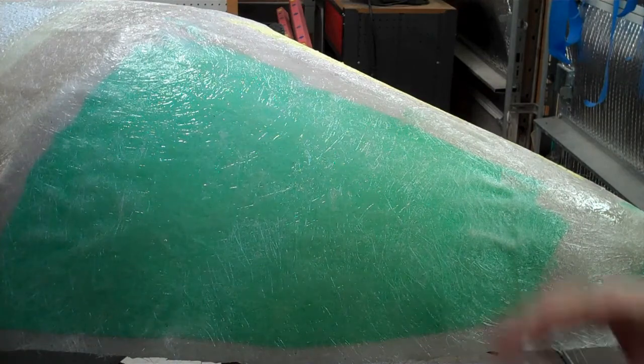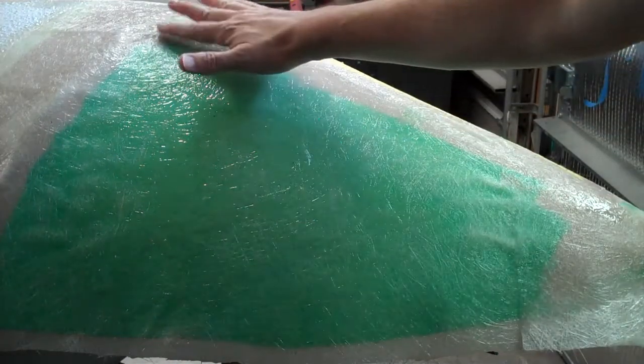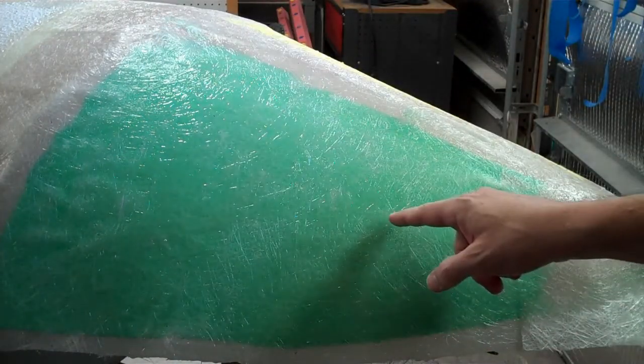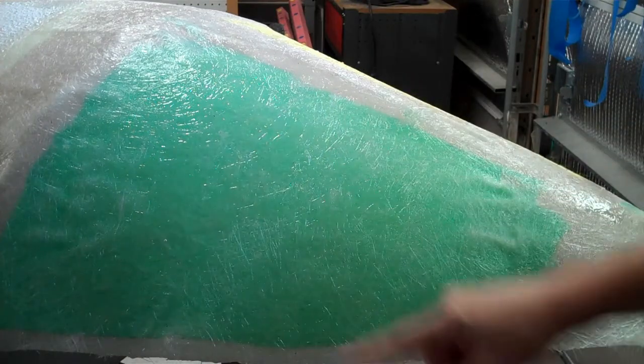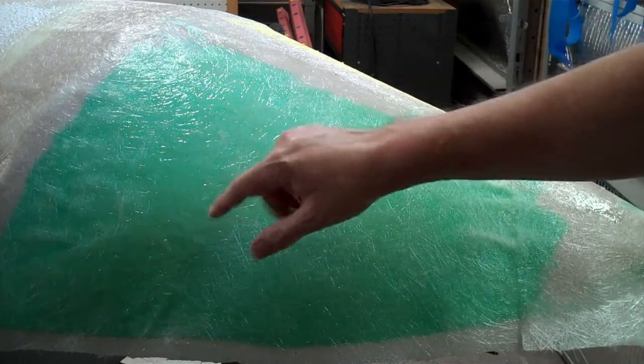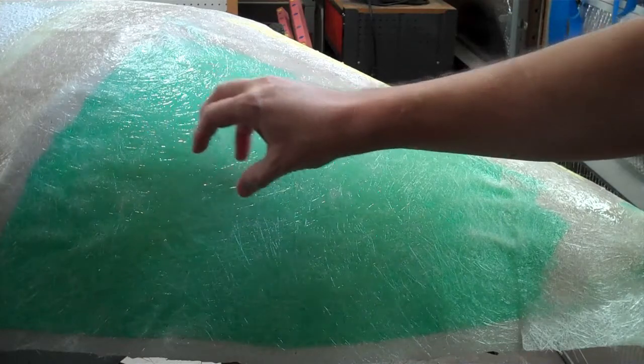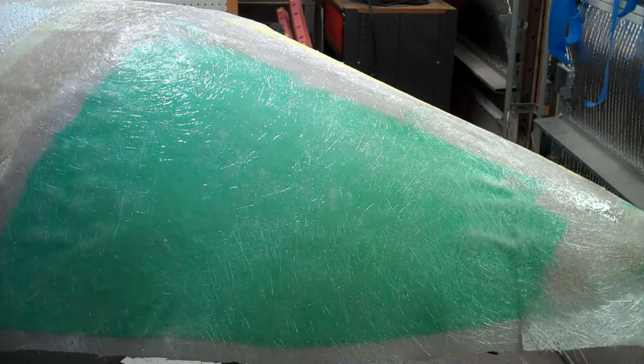So I'm going to be sanding this down a bit to knock down the high points, and if there's any strands sticking up still, it'll take those off, and any place where the epoxy is super smooth, sanding is going to knock that down and give it a rough texture so that the next layer will adhere to it pretty well.